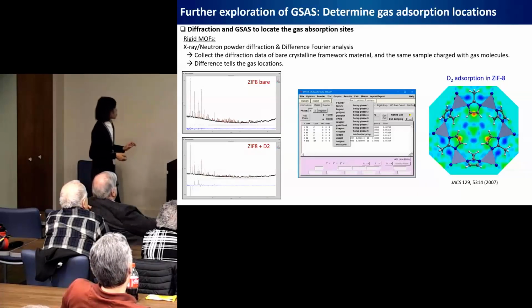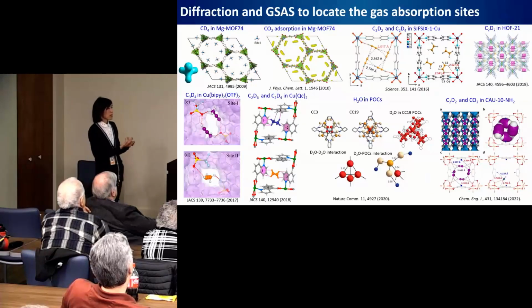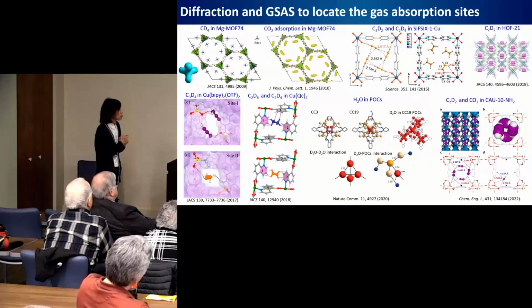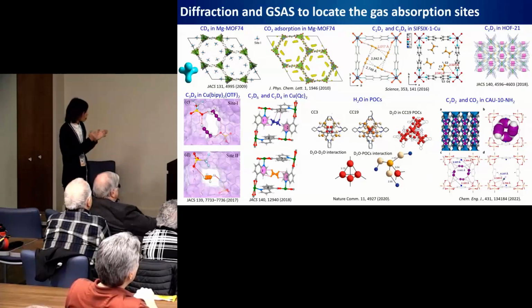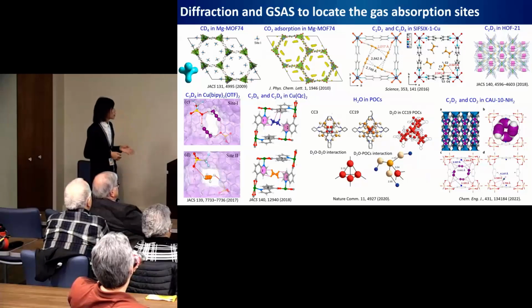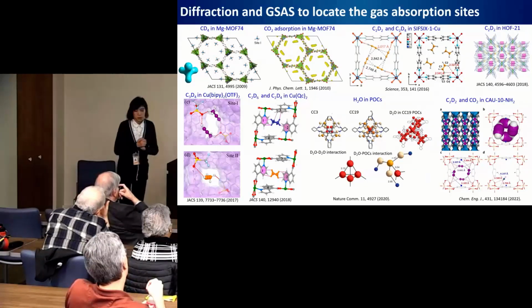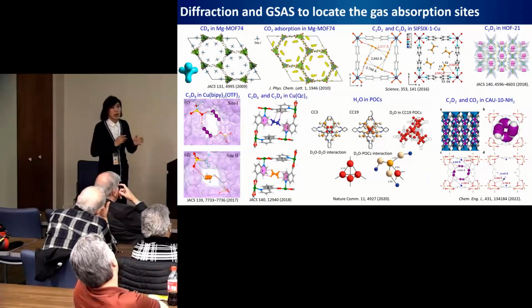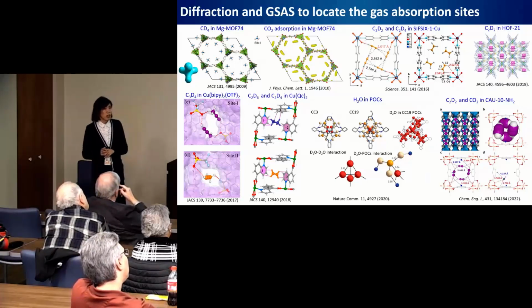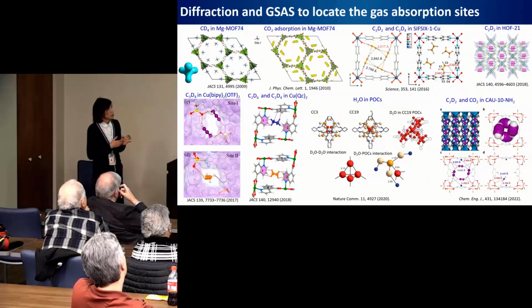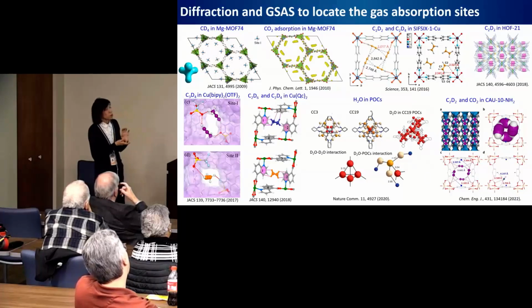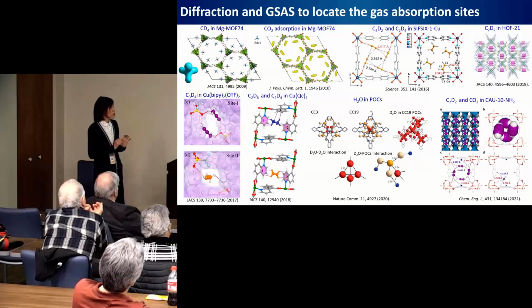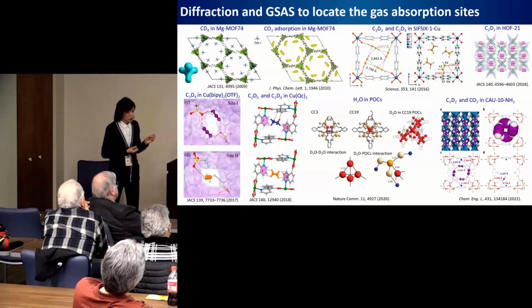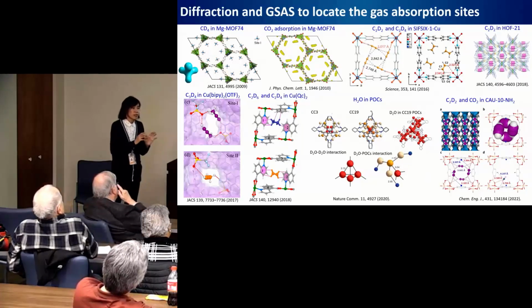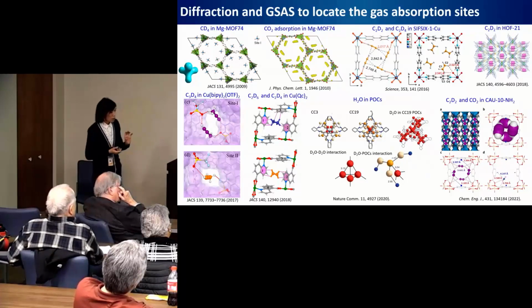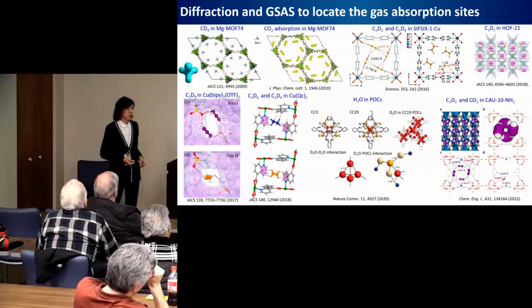So with this function, we have been able to determine the absorption sites for various gases in frameworks, for various gas absorption applications. For example, hydrogen, methane, carbon dioxide absorption, separation between different hydrocarbons, and water separation, etc. So once we determine the absorption site of those gas molecules within the framework, then we can understand the interactions between the molecules and framework, so that we can further modify the framework materials. For example, we can tune the pore size and pore geometry so that the framework can accommodate similar shape and size molecules. We can also tune the chemistry of the framework so that you can include open metal sites with coordinated metal, or we can introduce functional groups to enhance their affinity to particular gas molecules.